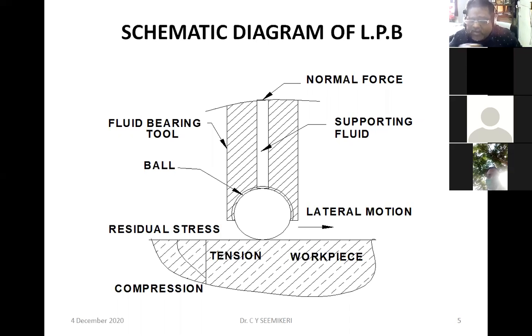Thereby, the component surface will not bounce back. So during high temperature applications, the residual stresses inculcated in the surface will stay together. They will not relax. In the case of hammering with a lot of intensity on the surface, because of larger cold work, the residual stress inculcated will relax when the surface of the component is exposed to temperature. So that is the beauty. There is a lot of research work there. I don't want to give you that dose in the beginning, but I told you the advantage of low plasticity burnishing against shot peening or other methodologies which apply force with more pressure or more intensity.